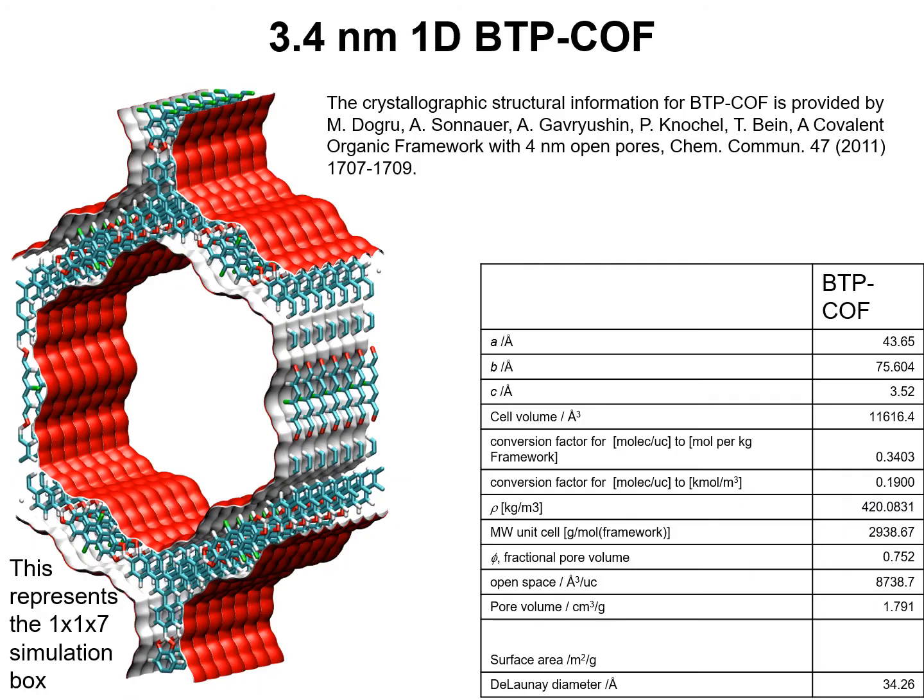Now let's have a look at pores which are larger than 2 nanometers, for which both molecule wall collisions and molecule-molecule collisions are important. In this case, we perform MD simulations for a 3.4 nanometer covalent organic framework called BTP-COF. It has one-dimensional channels that are hexagonal in shape.